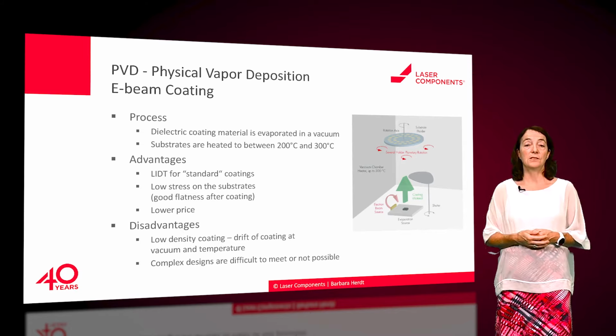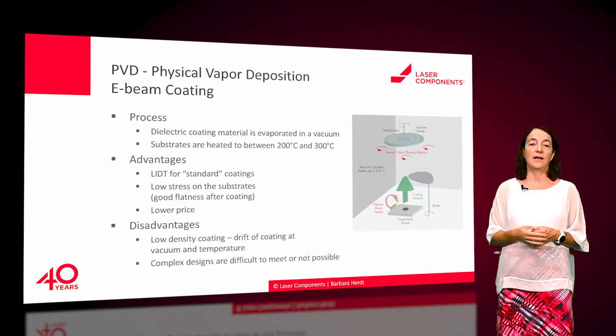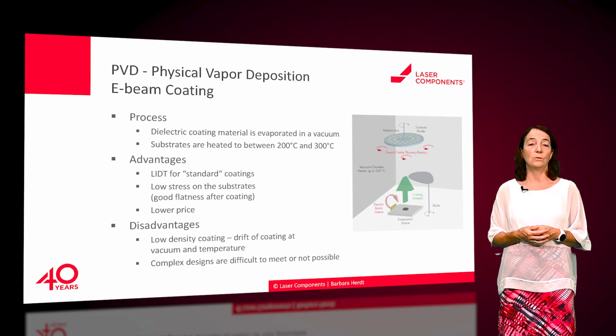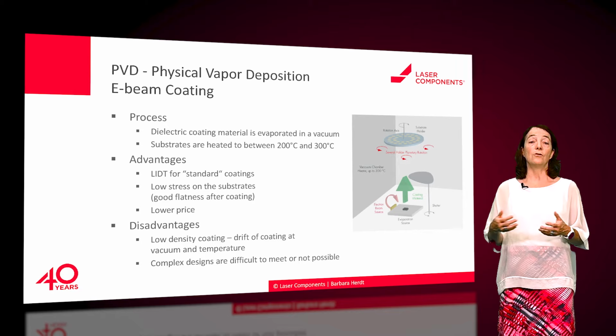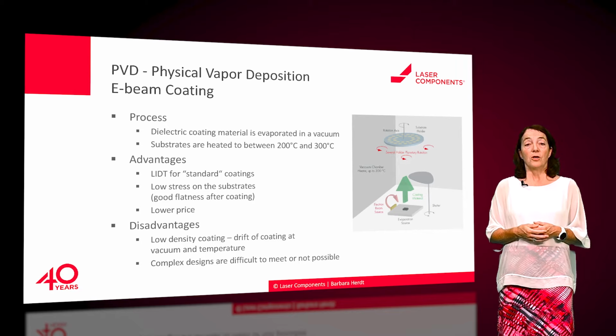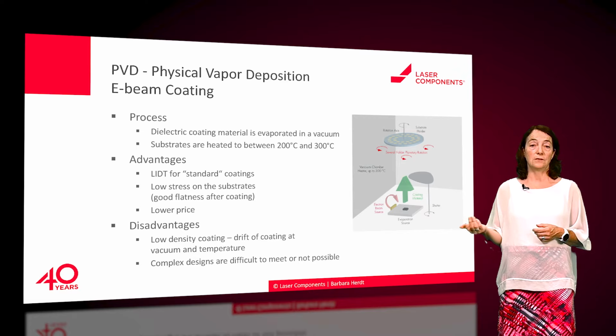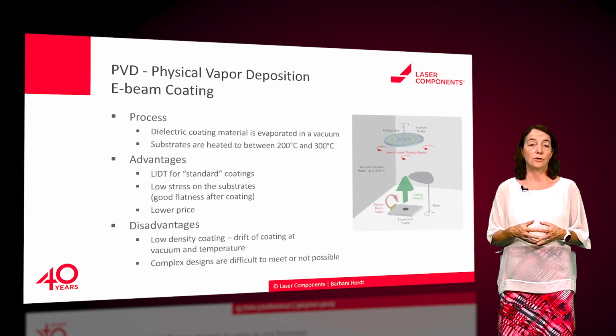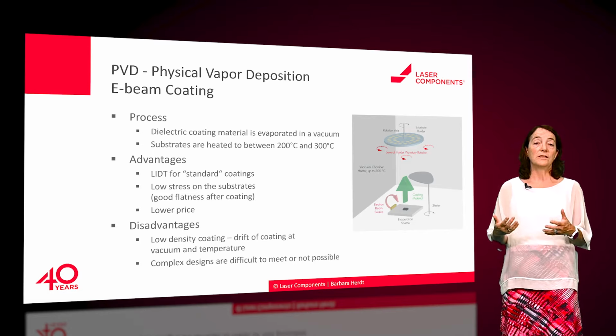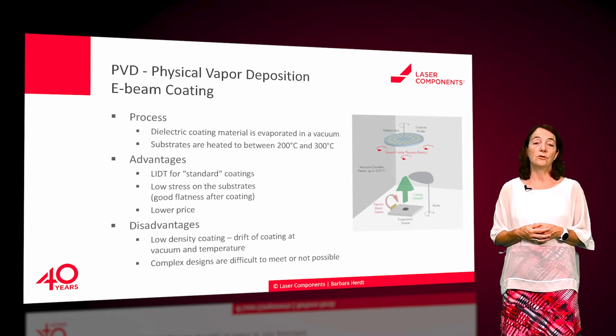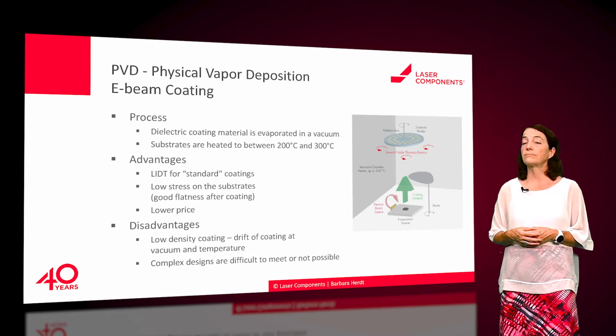But there are also some disadvantages. This is mainly driven by the fact that the coating is not dense, and for some applications, such as under vacuum or with temperature changes, the coating is drifting. Because of this temperature drift, the spectral measurement during the coating process is not working very well, due to the different environmental conditions during the coating process. Thus, for complex coating specifications, other technologies are preferred.